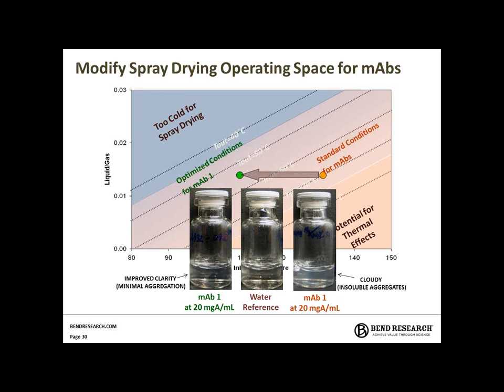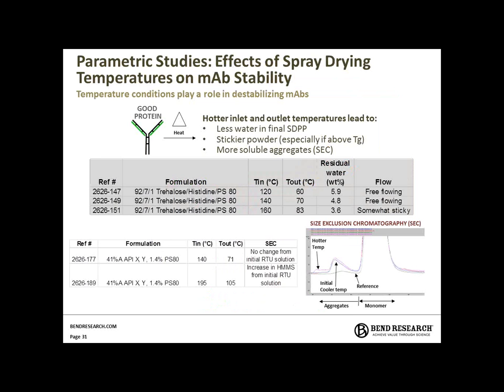In these 3 pictures in the middle of the slide, we see on the far right a cloudy solution, which is insoluble aggregates of mAb. In the middle image is the water reference, and the far left is our improved condition spray dry process, which led to improved clarity and less aggregation, justifying our process map and the rational spray dry process decision tree that we developed for this program.